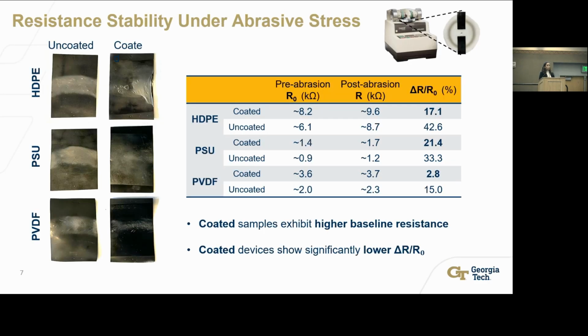Now, before moving on with the actual EDS performance, we finally have done an abrasion test setup. Here, you're going to see our equipment on the top right corner that uses some wheels to push some dust simulant onto the surface forcefully so that the samples are being abraded with the dust. And we have again taken a look at the sheet resistance measurements with a two-probe multimeter before and after the abrasion. And by using these values, we have again calculated the relative increases to the resistance with the abrasion damage.